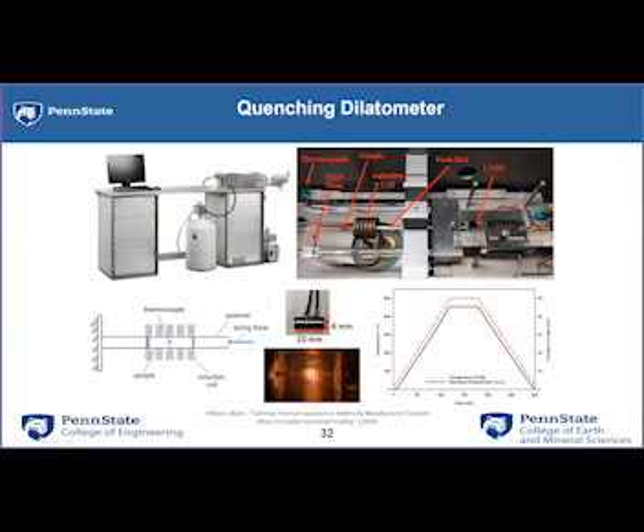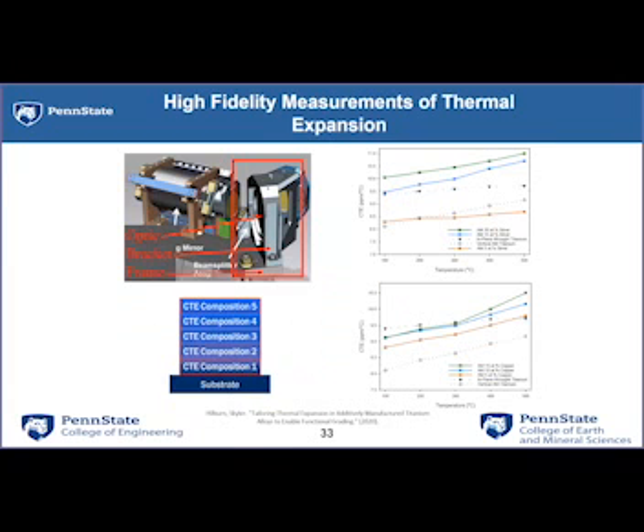So you see this liquid nitrogen, we can go down to about negative 150 degrees C. So we can start understanding transformations, and transformations of martensite through cryogenic heat treatments that you may be applying to different parts that you have, and starting to understand a little more of what's going on within the material, and maybe catching some things that you may not be able to see through more traditional techniques. And these are some of the high fidelity.